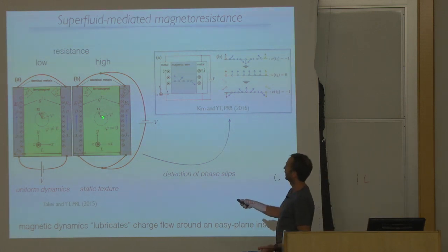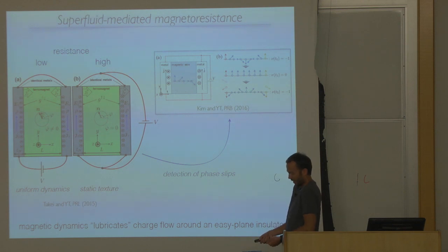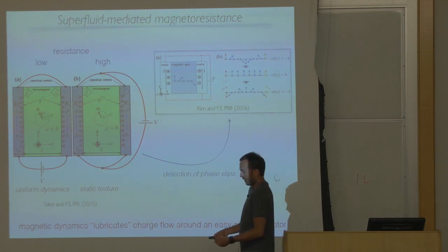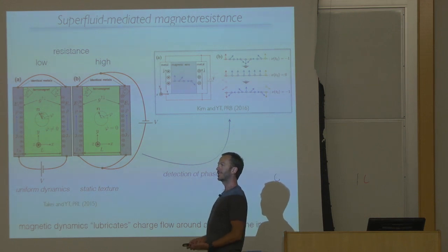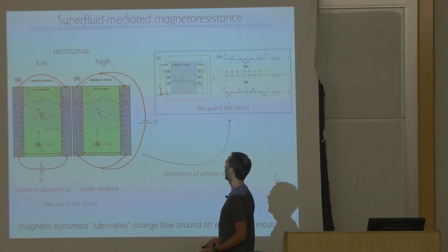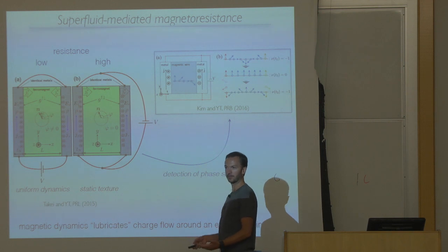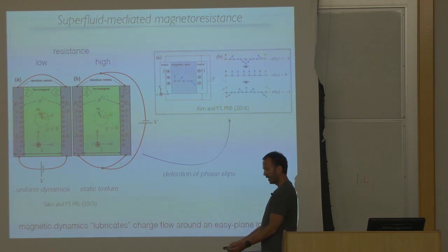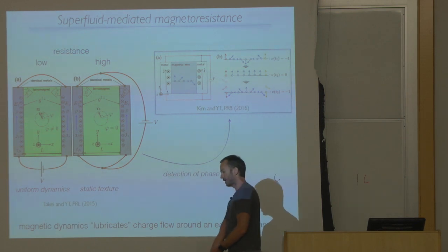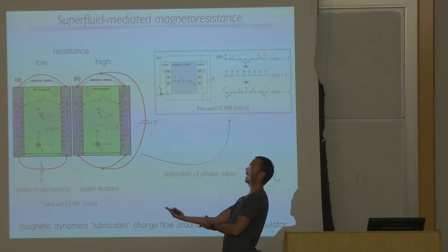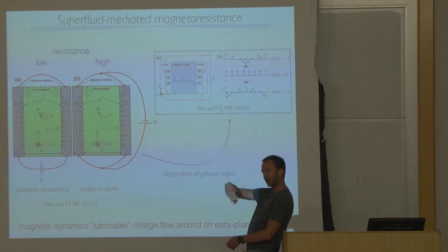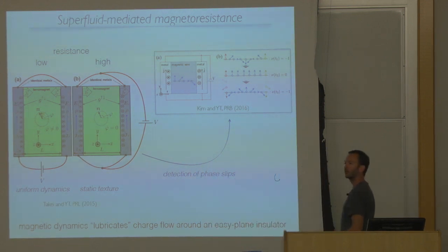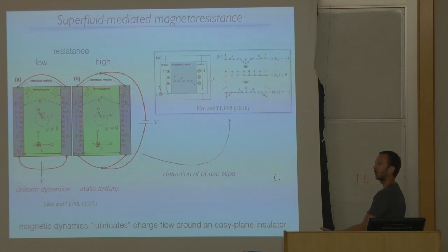So in general, this magnetic texture is a metastable state that tries to unwind. It's a state that costs finite energy. So the system will try to find a way to unwind. And that happens through phase slips. Basically, at some point, you will start creating vortices and anti-vortices in 1D. Magnetization ultimately will come out of plane, cross over the north or south pole, and ultimately unwind, either by thermal fluctuations or by quantum fluctuations, so thermal or quantum phase slips.